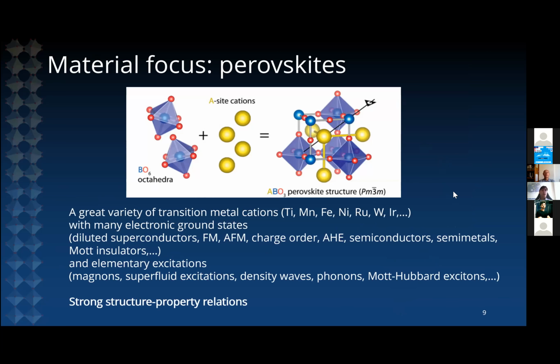So the material focus of our research are perovskite materials. And so we've chosen perovskites because these are systems that are characterized by strong structure-property relations. They're materials that are able to incorporate a great variety of transition metal cations. So we have a structural motif, which is a BO6 octahedra, where B is a transition metal, and a lattice of A-site cations. When you bring these two together in a high temperature phase, you have a cubic crystal symmetry that is able to accommodate a big variety of cations, and to these various cations you have many electronic ground states that become accessible. So in our lab we study systems from dilute superconductors to multiferroics, going through various types of magnetic systems.